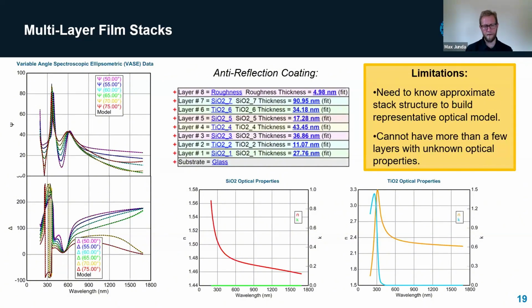And the key thing here is that this particular coating is actually just 2 different materials alternating. It's silicon dioxide and it's TiO2. And so what we've done is we've assumed that all silicon dioxide and all TiO2 layers have the exact same properties. And then what we're effectively doing is only fitting the thicknesses. And so this kind of gets at some of the limitations of what you can do with multi-layer film stacks. In this case, it works okay because we're fitting the individual thicknesses of the layers, and we've constrained the number of unknown layers that are present because there's really only 2 things.